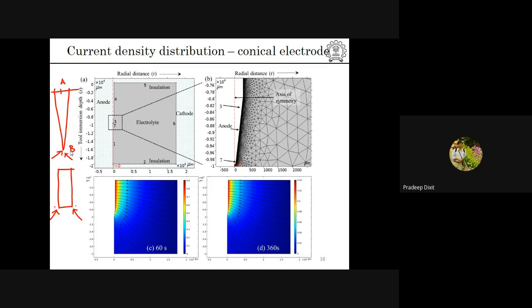So in practical ECM, at point B, the material dissolution rate is going to be higher than at point A. But if you recall, Faraday's law does not talk about location-dependent material removal behavior. This is totally dependent upon how the current density is concentrated at different points. So it is very important for anyone to find out the distribution of the current lines in any electrochemical dissolution process.